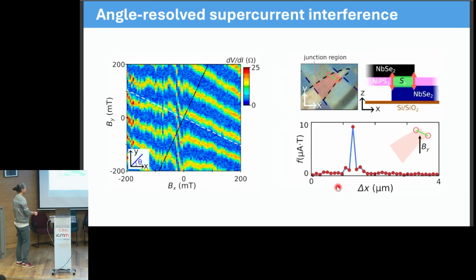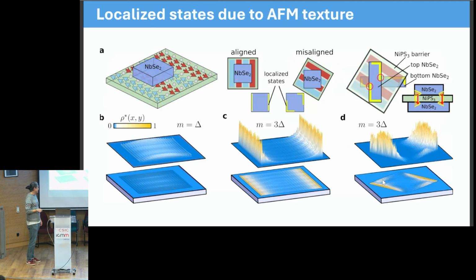And when we do a Fourier transform, again, we see that it's consistent with the dimensions of our sample. And the width of these localized states is very narrow. It's below 100 nanometers, maybe below 15 nanometers. So they're truly localized in a sample that has maybe 5 to 10 micrometer lateral dimensions. We have two localized states that have maybe an extension of 50 nanometers. And that's it. This is what carries the transport in this device. Well, to us, highly unexpected. And as experimentalists, we don't have an explanation for this.